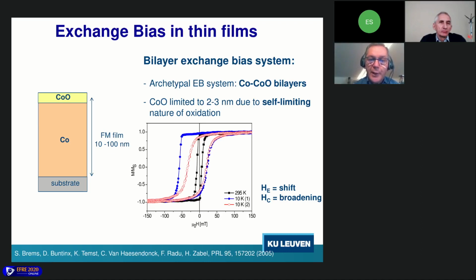Now, if you look at the magnetic hysteresis loop of such a system, then here in black, you see the hysteresis loop at room temperature. Nothing special about it. It's just a ferromagnetic hysteresis loop. But when you cool down to below about 150 Kelvin, then you will establish antiferromagnetic order in this cobalt oxide. And then you see this blue hysteresis loop. And you see, like in the cartoon before, that it is much broader than before. So you gain in coercivity of the layer, and it is also shifted.